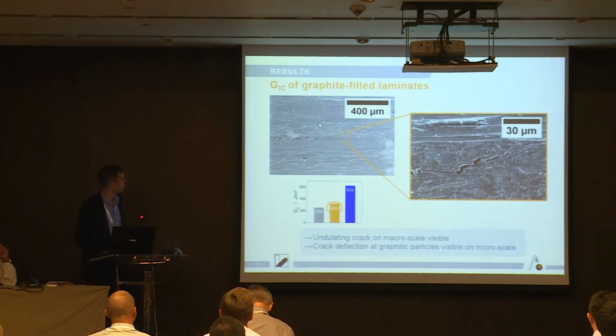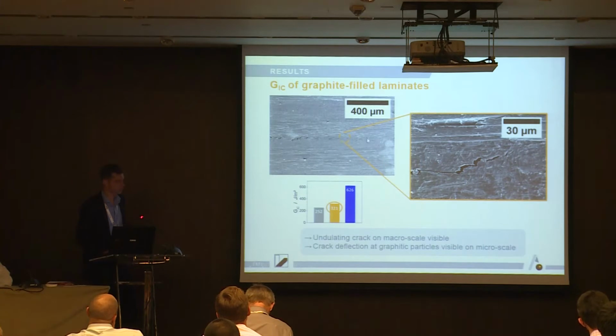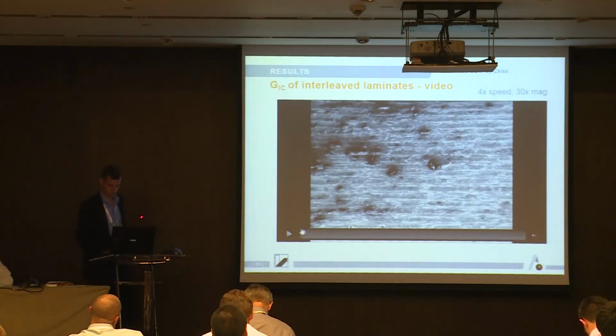I hope you see a bit that here the crack is moving and it's undulating, so it's not a straight crack. It's better viewable hopefully here in this picture. So you don't see the straight crack that you observed before, but you have some undulation in your crack. And this is much better viewable at higher magnification. You only have this rather low increase in the fracture toughness, but for the other material, the material with the thermoplastic interleaves, you can see that it's better.